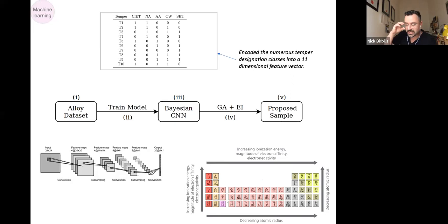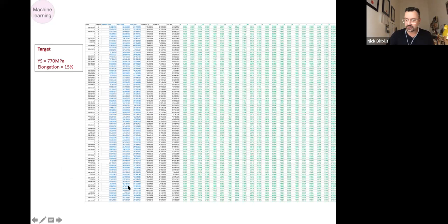So machine learning, if it's trained, can take the best of the best in terms of expert systems because the data it's fed embodies the individual designers that have generated those alloys. So I'm not going to go into those details, but it hasn't been a simple task because there's so many different heat treatments for aluminium alloys that we had to encode tempers using a feature vector as to whether alloys were cooled from an elevated temperature, naturally aged and artificially aged and cold worked, solution treated and so forth. So in order to give a numeric recipe to a computer that it understands for what are non-numeric and human-derived inputs.